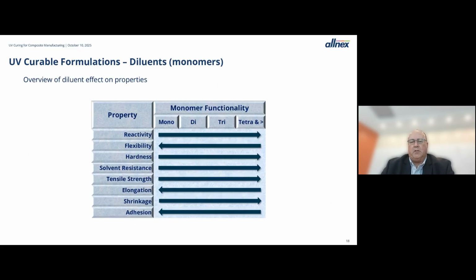And this chart just shows the other effects that monomers and monomer functionality can have on properties. So as you increase functionality, reactivity tends to go up, solvent resistance, tensile strength, and shrinkage tends to go up. Conversely, flexibility and elongation tend to decrease as you go higher and higher in functionality. So while monomers are used primarily for their diluent effect, just be cognizant of the fact that they also have an effect on other properties.